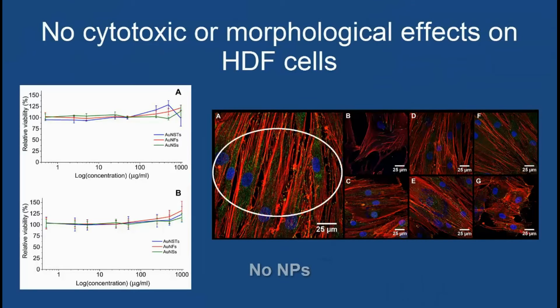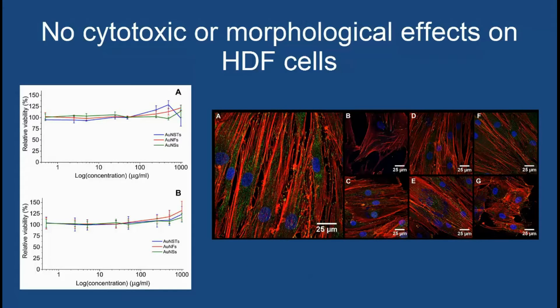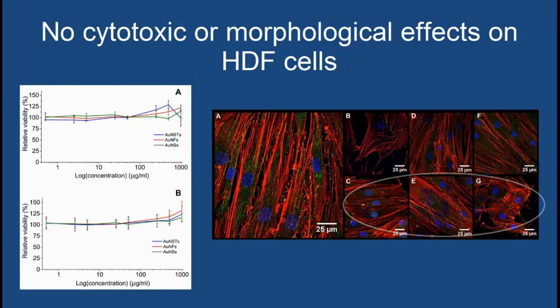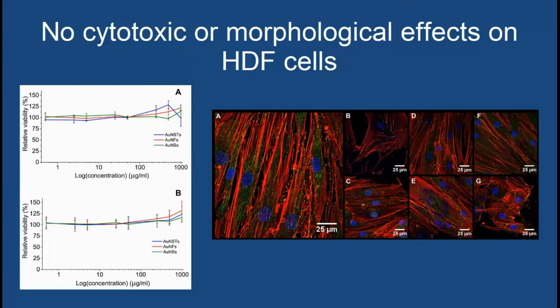The particles were evaluated for cytotoxicity towards human dermal fibroblasts and no significant cytotoxic effect was found using MTS viability assays. Nor were any morphological or cytotoxicity-indicating changes detected in the cells with confocal fluorescence microscopy, even upon exposure to high concentrations of the particles.